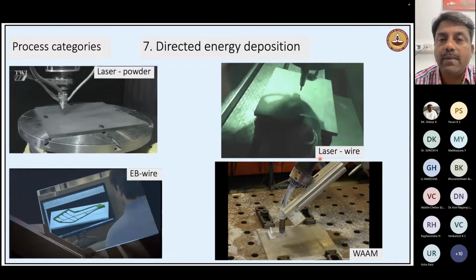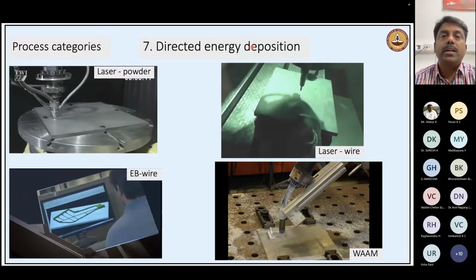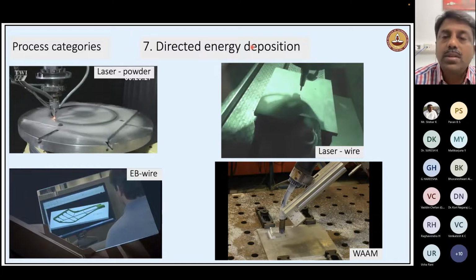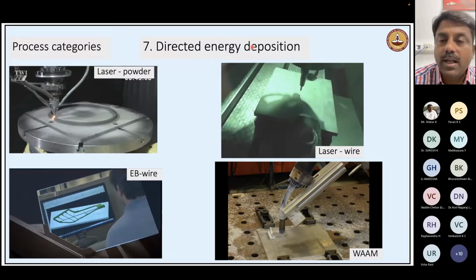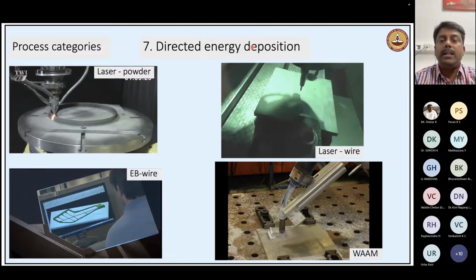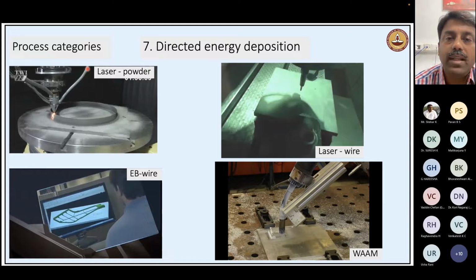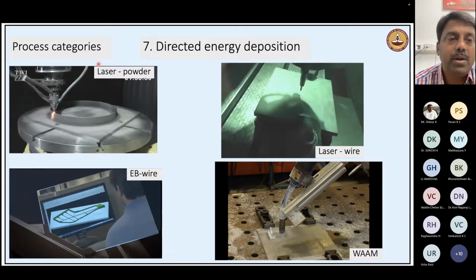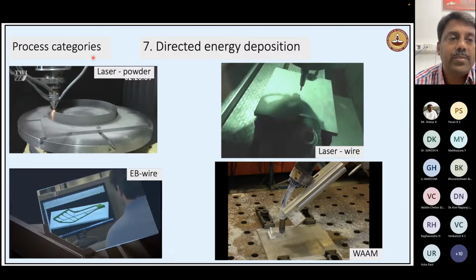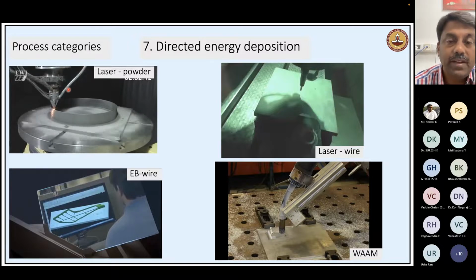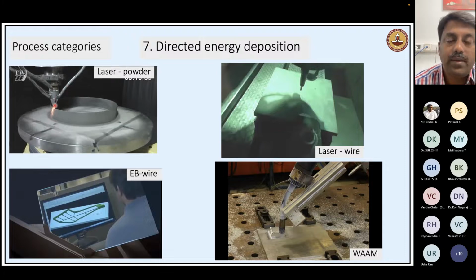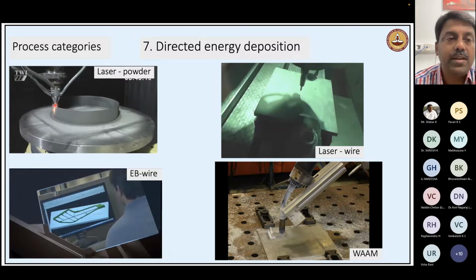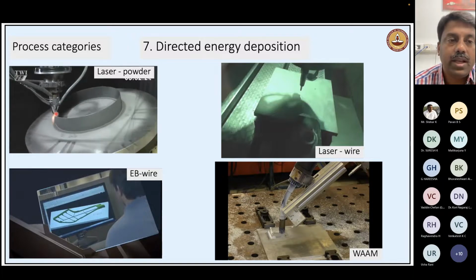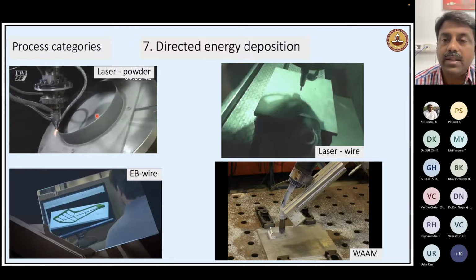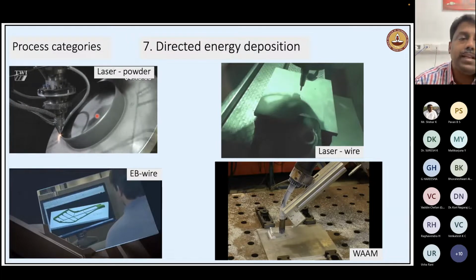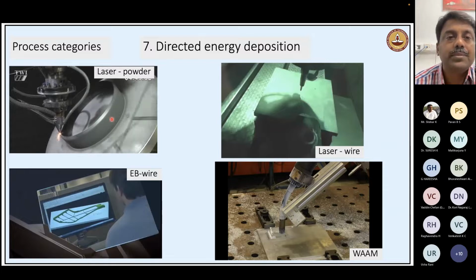The seventh technique we have is known as direct energy deposition. So DED is similar to welding, or cladding, laser cladding. In this process, a feedstock is fed. Feedstock can be either powder or wire. In this case, what you see in the video at my pointer, a laser source and a powder. Powder is fed onto the laser, and because of the laser interaction the powder melts, and then it is deposited on top of a previously solidified layer, and then we keep adding the layers to produce a final part.